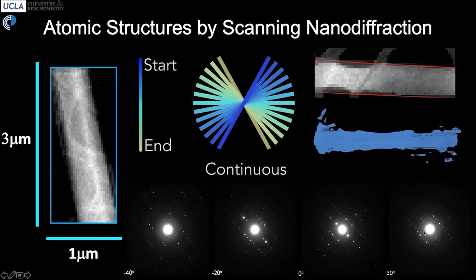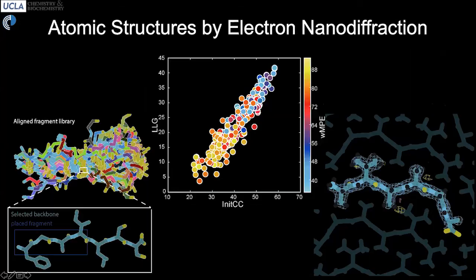And at the same time, we can actually reconstruct a real space rendering of that crystal itself. And so this is what we're actually reconstructing the crystal structure of, this region of space that is segmented here. And so from that region, we're able to obtain an atomic structure for, in this case, a peptide molecule. And that peptide molecule is shown here. The density retrieved from the data that was collected is shown in the blue mesh. And then the ball and stick model is built into that density with reasonably good statistics.